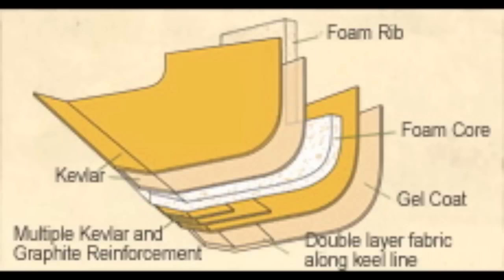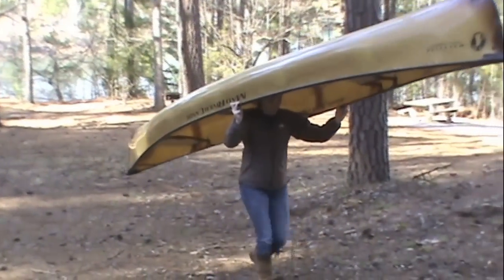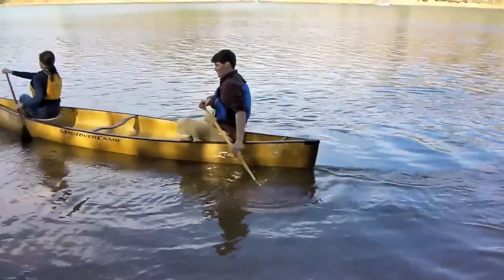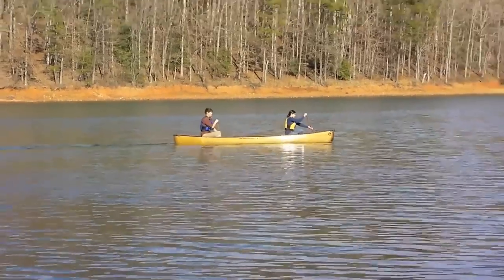And then the foam is capped on top with multiple layers again of Kevlar to again seal the foam and also provide the strength. Kevlar is extremely strong, very lightweight. It has 5 times the tensile strength of stainless steel. So it's a very, very durable material. It has a lot of give to it, so it allows it to suffer an impact, absorb the impact, and deflect back into original condition.